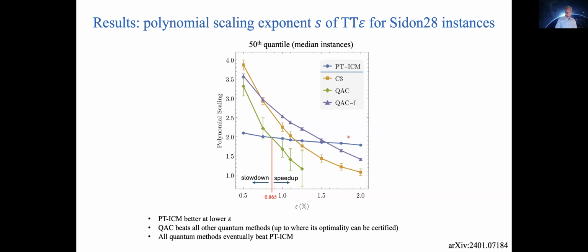So PT-ICM, that's the slope of the blue curve. The C3 in orange, QACF in purple, and QAC in green. So QAC has the best performance, and at an optimality gap of about 0.86, we see a transition from a slowdown where the slope is larger than PT-ICM to a speedup where the slope is clearly less than PT-ICM. So this is the demonstration of a quantum speedup.